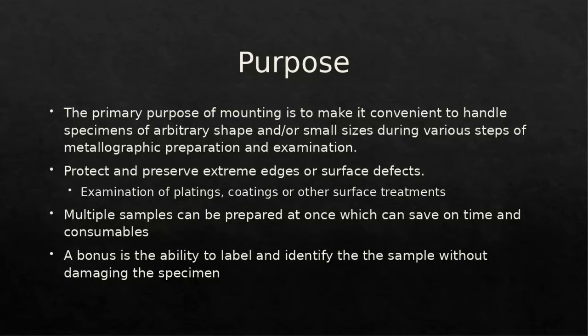Also a nice thing is the fact that you can prepare multiple samples at once. Just a rule of thumb, if you're going to mount more than one sample together in one mount, it's best if they are of similar material. Say, for instance, all of it be 6061 aluminum. One can be annealed, one can be hardened. That's fine. It's still the same material, versus one copper and one tool steel. You're not going to put both of those together in the same mount because of the hardness difference, and you'll also see that the copper will never polish out nicely. So multiple samples can be prepared at once, which saves on time and consumables, which are the biggest uses when it comes to materials in the lab.